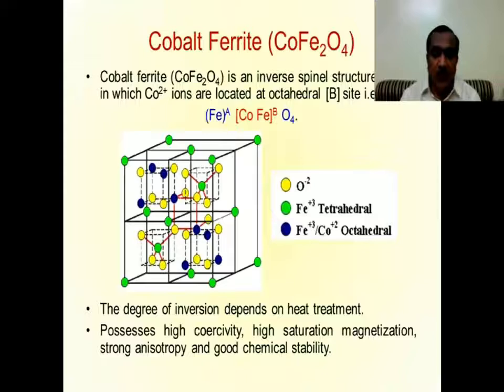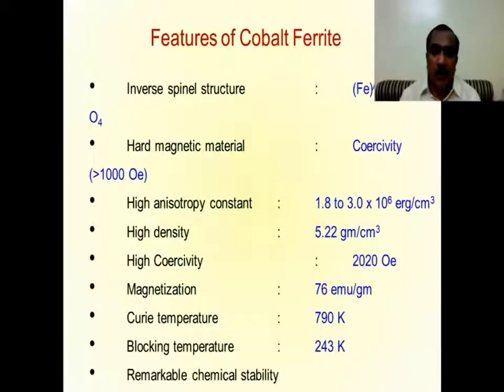Secondly, it has a high coercivity, it has a high saturation magnetization, it has a high anisotropic constant, and moreover, it has a good chemical stability. So cobalt ferrite, among all the rest of the ferrites, that is nickel ferrite, magnesium ferrite, zinc ferrite, performs well and shows better characteristics. We can observe the salient features or the important characteristics of cobalt ferrite.